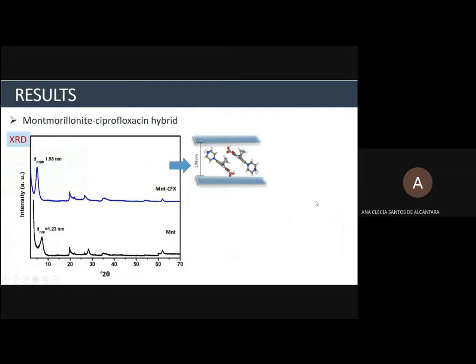The results. In order to investigate the formation of the intercalation compound, these materials were evaluated by XRD measurements. In this case, it's observed that the 001 reflection from pristine montmorillonite is shifted towards lower degrees 2 theta, displaying in this case a new basal distance of 1.98 nanometers, which indicates the intercalation of ciprofloxacin molecules between the layers of the montmorillonite.